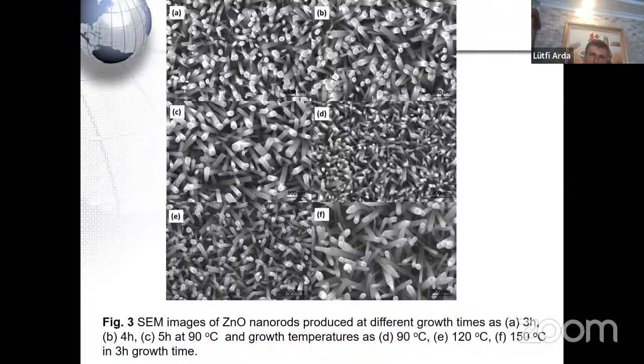Also, note that the hexagonal structures start to deteriorate, resulting in secondary nucleation on the top of the rod as the growth temperature increases from 90 degrees to 120 degrees. When the temperature reaches 150 degrees, look at the last figure, pyramid-like structures are found.